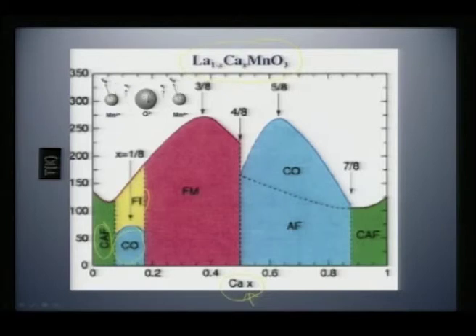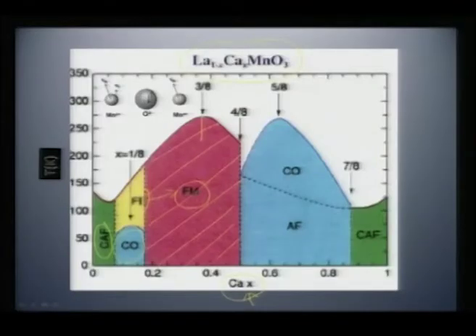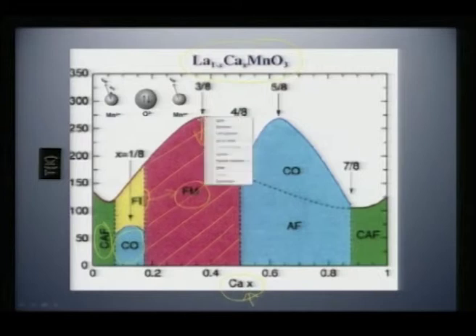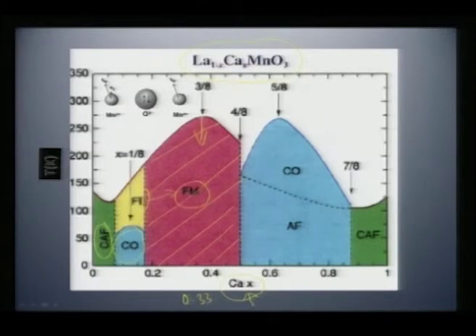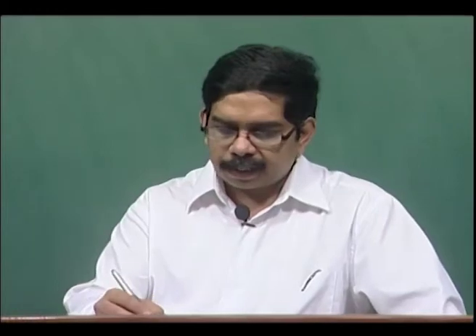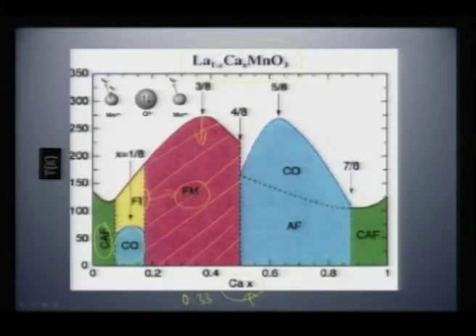And once you go further doping with calcium, from a ferromagnetic state it goes to a ferromagnetic metallic state, and this is the regime of interest for us, because this is the place where a lot of applications can be harvested. This can be used for a variety of applications, because this is the state at which there is a huge loss in resistance. And as you would see in this regime, for a nominal composition of 0.33 calcium, the ferromagnetic transition becomes maximum, and after that it starts fading down, but then it is also affected by another big domain, which is either charge ordered or antiferromagnetically ordered.